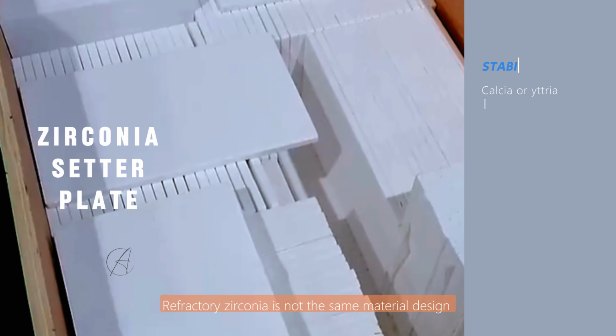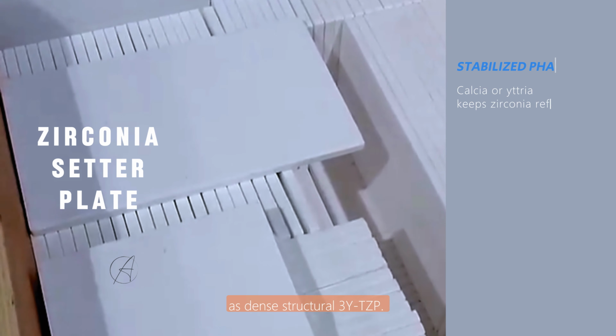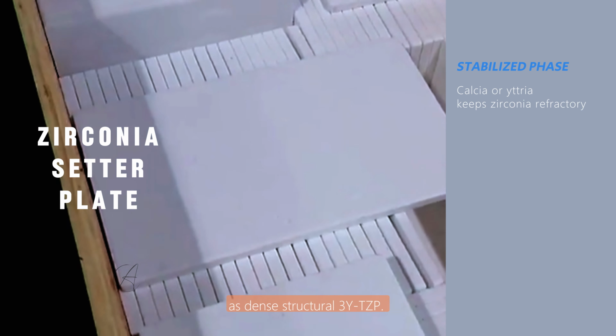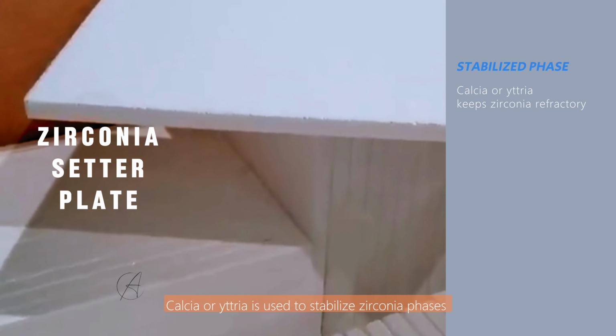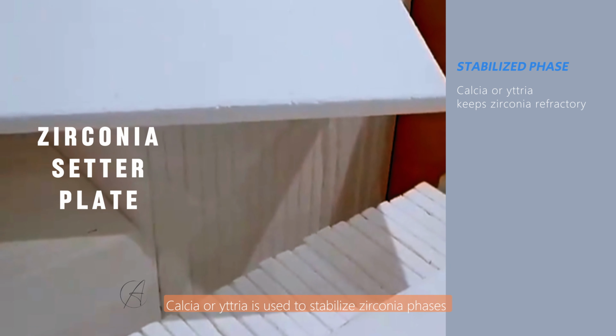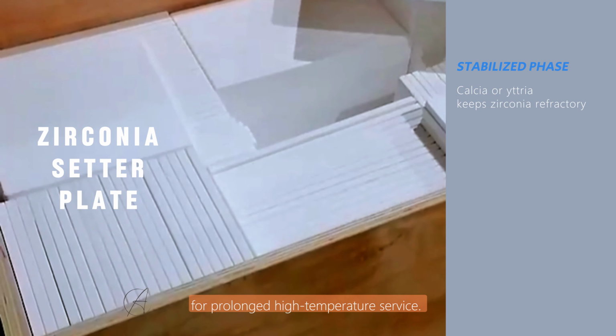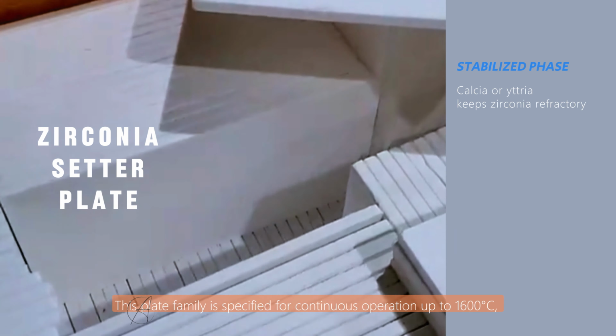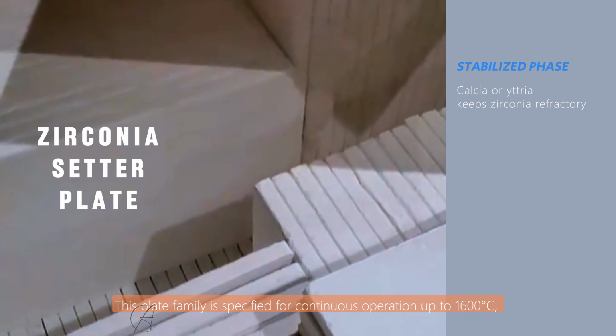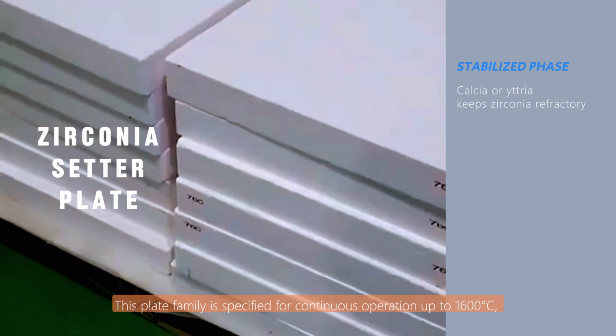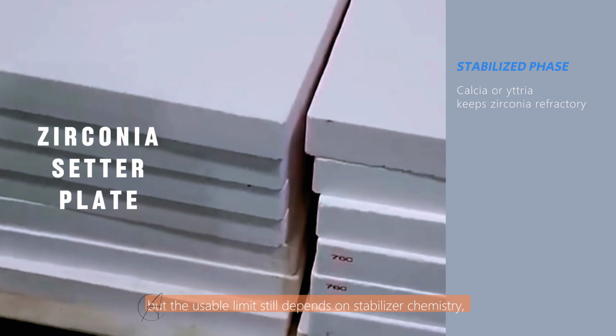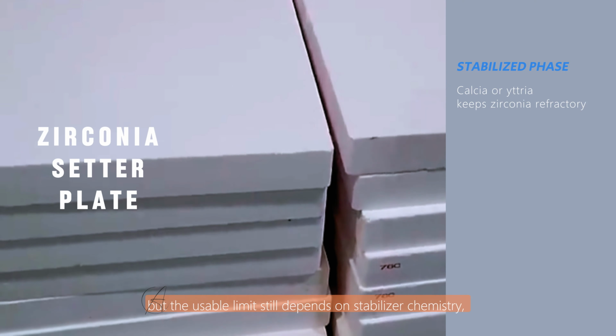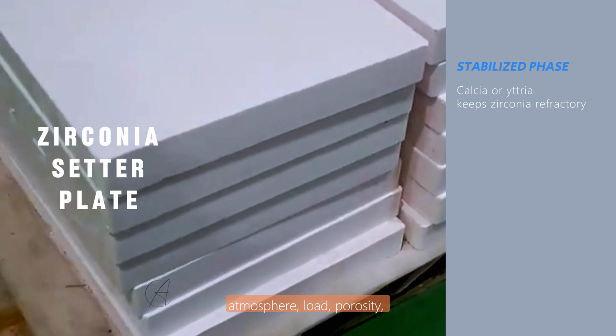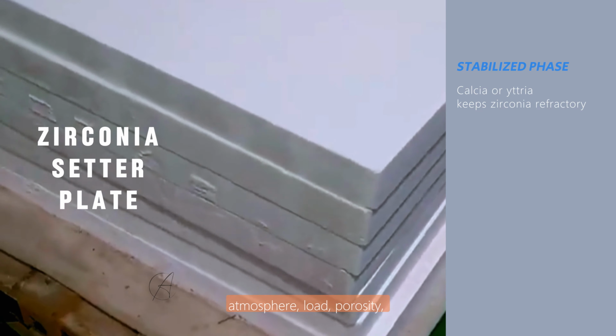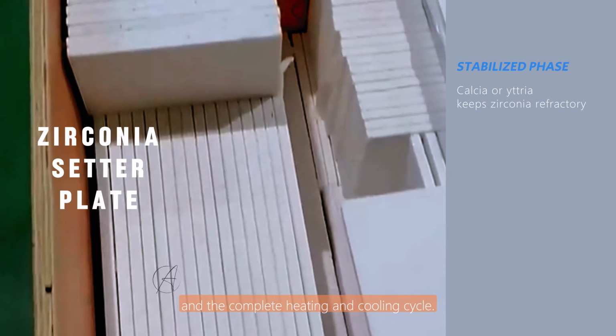Refractory zirconia is not the same material design as dense structural 3YTZP. Calcia or yttria is used to stabilize zirconia phases for prolonged high-temperature service. This plate family is specified for continuous operation up to 1600 degrees Celsius, but the usable limit still depends on stabilizer chemistry, atmosphere, load, porosity, and the complete heating and cooling cycle.